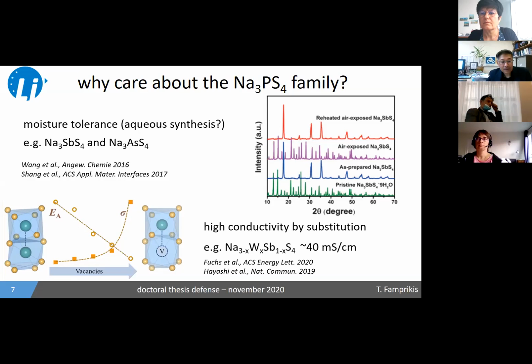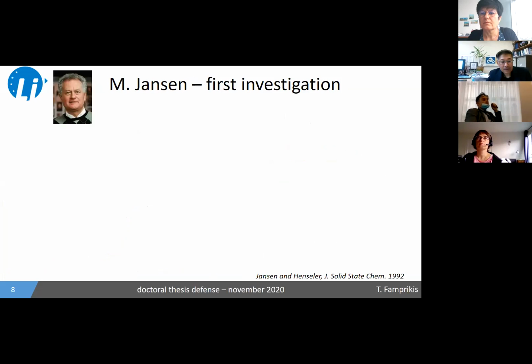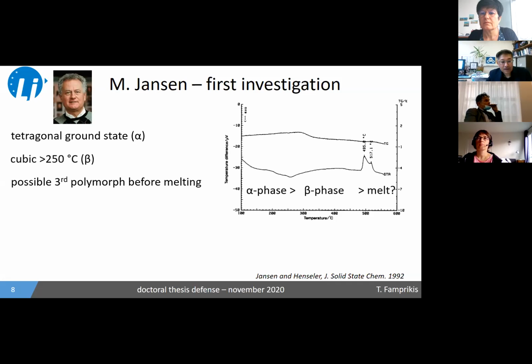So with that, I would like to very quickly describe the state of the art on Na3PS4 right before my thesis, 4 years ago. The first work considering Na3PS4 as a solid electrolyte was performed by Martin Jansen in 1992, who solved the room temperature stable ground state alpha in the tetragonal space group. He also showed that there's a cubic polymorph appearing upon heating above 250 C. And using these thermograms shown here, they observed this bizarre doublet peak, which they assigned to melting. And they hypothesized also that there might be a third polymorph appearing right before melting.